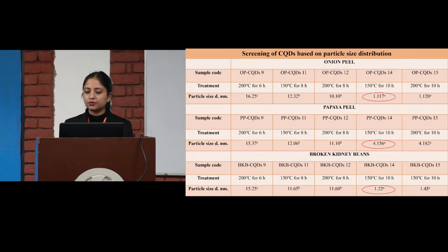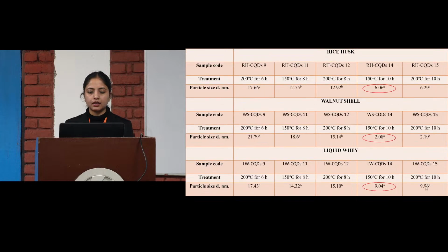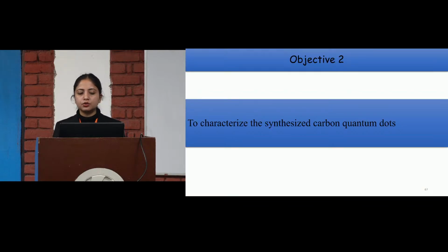This is the final table of the particle size, as we selected only the carbon quantum dots with the least particle size. For the onion peel, the least particle size is 1.17, at 150. When we synthesize the onion peel at 150 degrees Celsius for 10 hours, we got a 1.117 nanometer particle size of the onion peel derived carbon quantum dot. For papaya peel, that is 4.156, and for the broken kidney beans, that is 1.22. Then rice husk 6.06, walnut shells 2.08, and liquid whey 9.04. As the particle size is smaller, the fluorescence properties are good. So the least particle size has good sensitivity towards the detection of the packaging material.